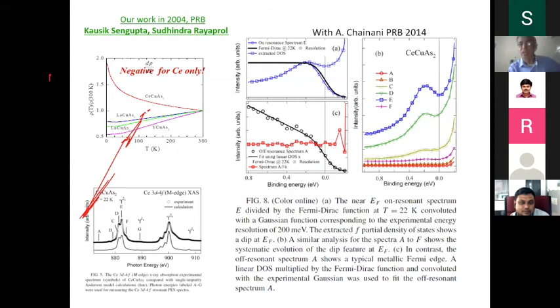The 4f electron, when it participates in bonding under favorable circumstances, can create a pseudo gap. Like you talk about high temperature superconductors, you can also have a pseudo gap. That gap is responsible for the negative temperature coefficient of resistivity. And interestingly, these are the materials where you also see a large thermopower. It is hoped that such materials, if they can be tuned, can be used for thermoelectric application. This is very important from the energy angle.